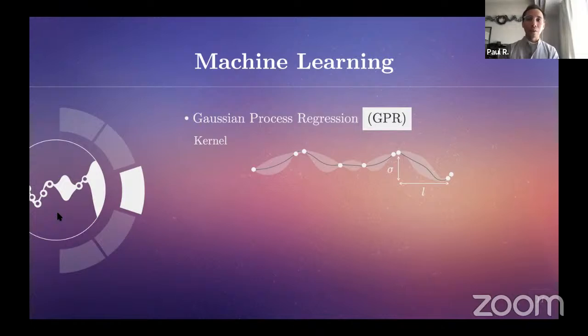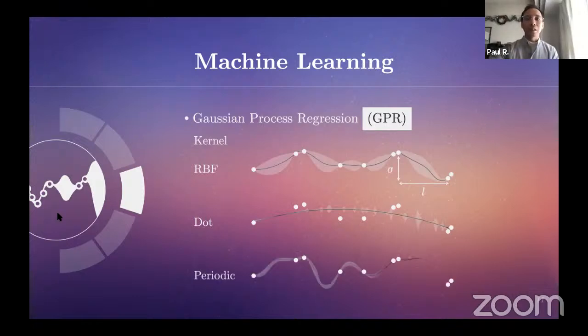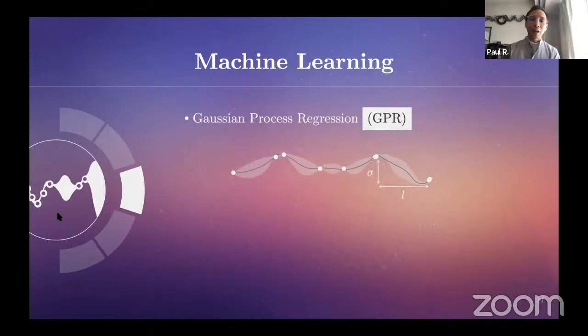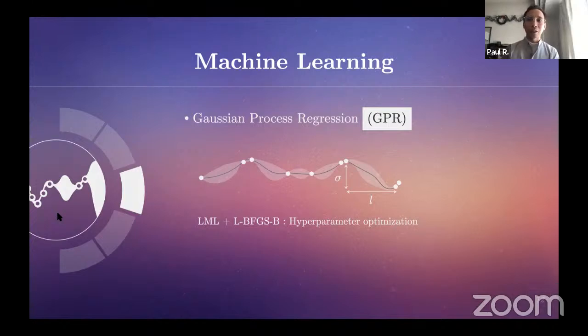Different kernels lead to different models. For example, a radial basis function or RBF kernel would yield a somewhat balanced model, whereas using a dot product kernel would return a more simple and much smoother model, which might underfit the data. On the other hand, using a more complex kernel like a periodic kernel would result in a more complex model but may cause overfitting. The GPR hyperparameters are optimized by maximizing the marginal likelihood using a gradient optimization algorithm such as the limited-memory Broyden-Fletcher-Goldfarb-Shanno algorithm.